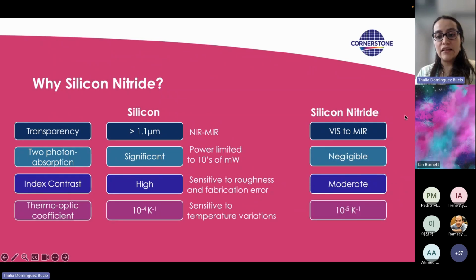On the contrary, silicon nitride has a thermo-optic coefficient which is one order of magnitude lower than that of silicon, which means that it has the potential to be less sensitive to temperature variations.